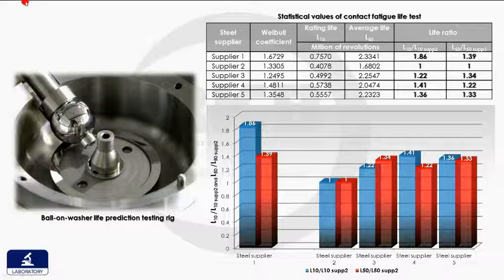The evaluation was conducted in a life prediction testing rig with a maximum contact stress of 4,200 MPa and a maximum speed of 2,040 RPM. Each of the 5 testing groups contained 16 test specimens. For each group, the tests were performed until the fatigue failure of all specimens. The statistical values listed in the table and depicted in the graph bar point out that the test specimens of the first supplier presented the highest values for both rating life and average life.